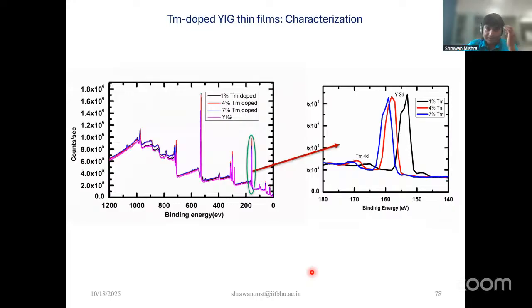Okay, so this is another detail of the thulium doped garnet film, and as you can see, this is the XPS survey spectra. Now we try to compare how the thulium doping actually affects the yttrium binding energy. The black one is 1% thulium, the red one is 4%, and this blue one is 7%. As we increase the doping concentration of thulium, the yttrium binding energy is influenced. So we can presume that thulium and yttrium are in direct correlation at a dopant site. So thulium is directly replacing the yttrium site in the garnet lattice.